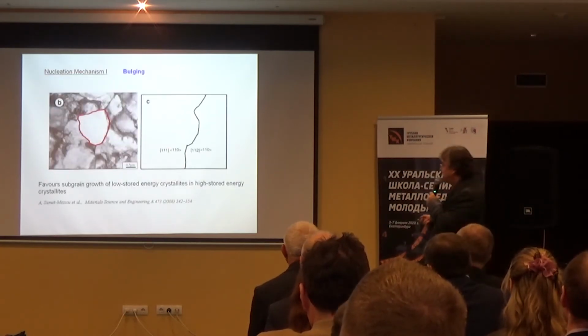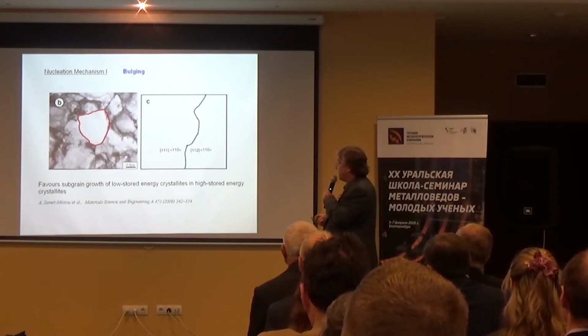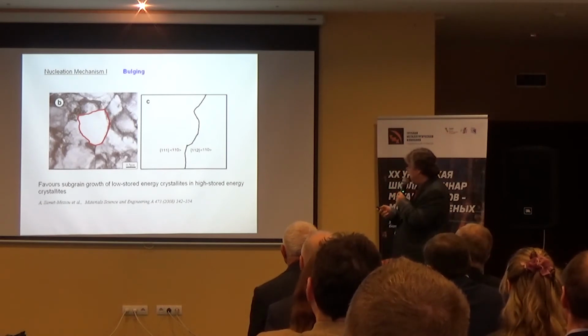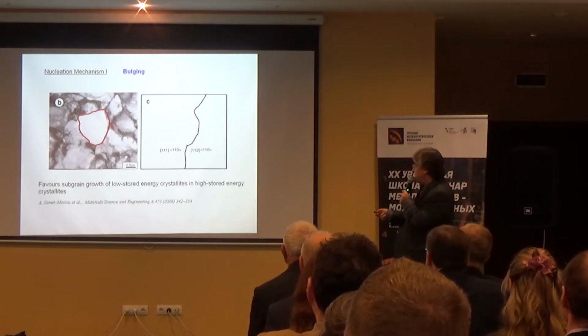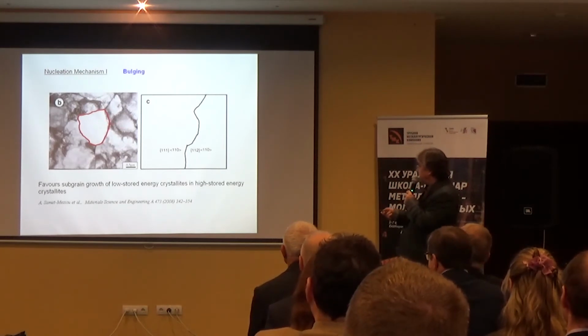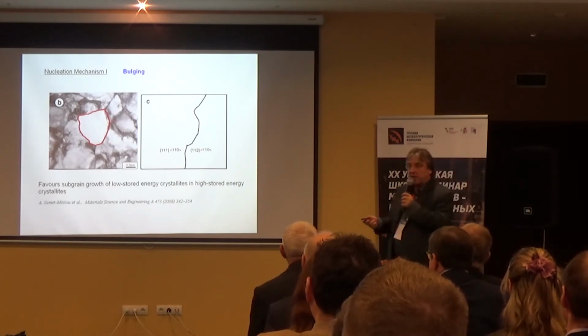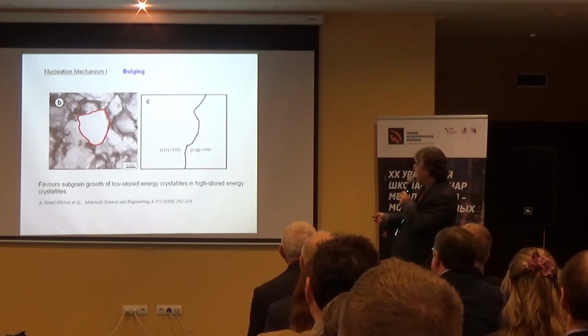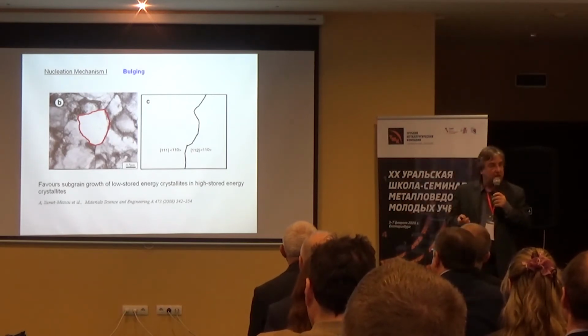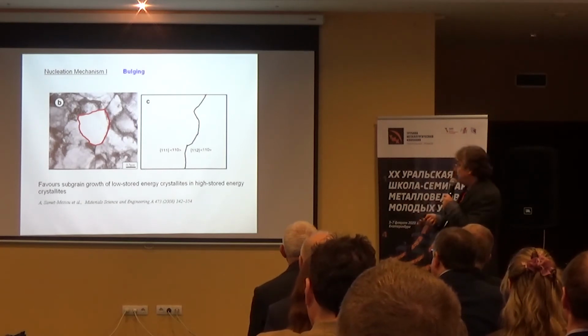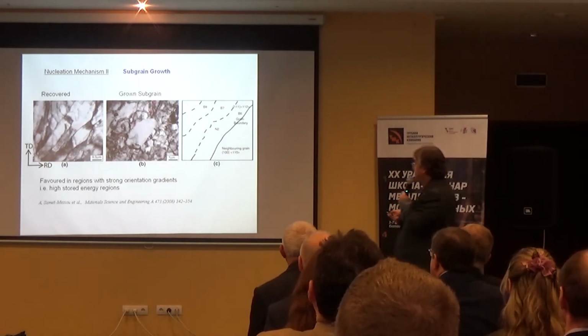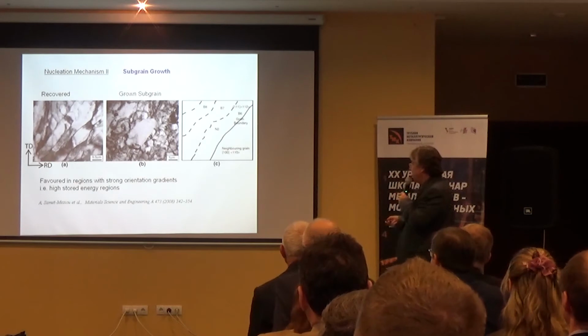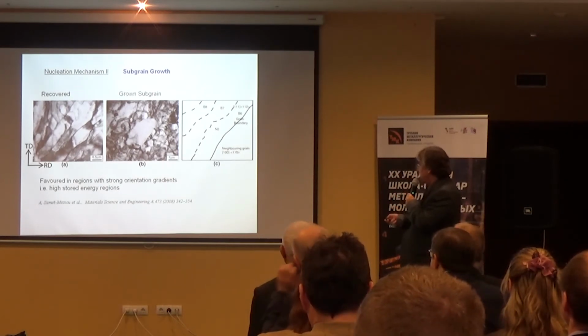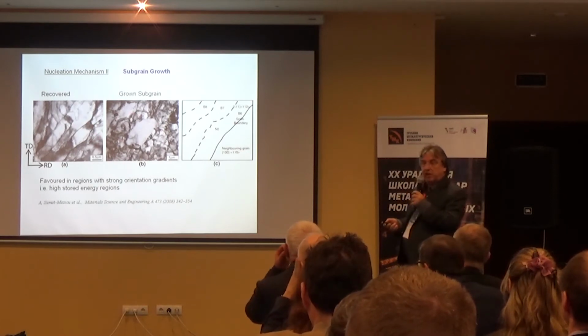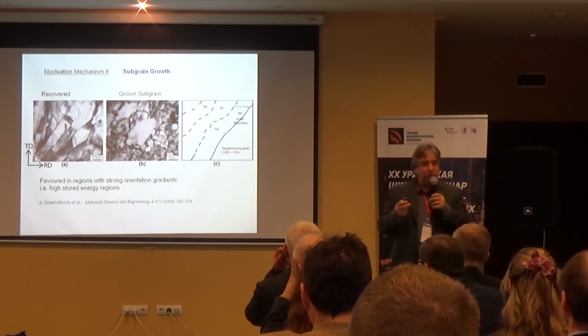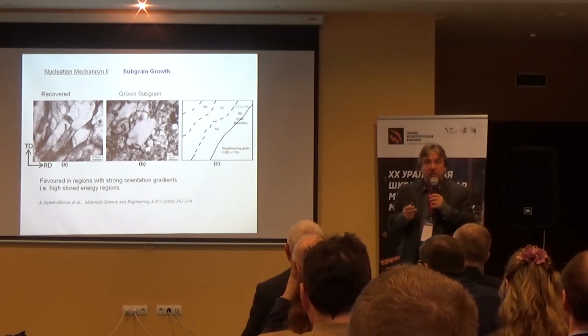Now there have been described in literature various mechanisms of nucleation which are of importance. Very well known is the so-called bulging mechanism or the strain-induced boundary migration mechanism. This is where you have a relatively dislocation-free cell which bulges out in the neighborhood of a cell with higher dislocation density, with higher deformation energy. So then you also have another mechanism which is subgrain growth. So in subgrain growth, you have in fact a cell which starts growing abnormally. And it's a little bit like abnormal grain growth, but on the level of the subgrains, not on the level of grains.